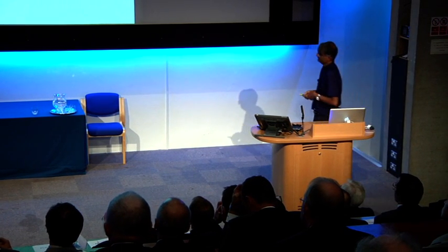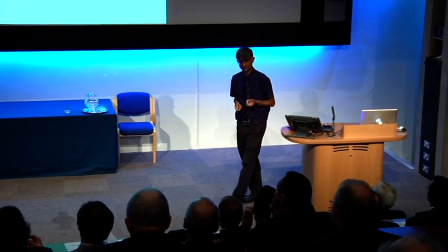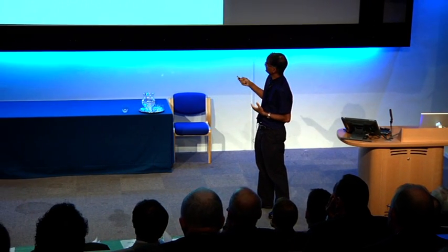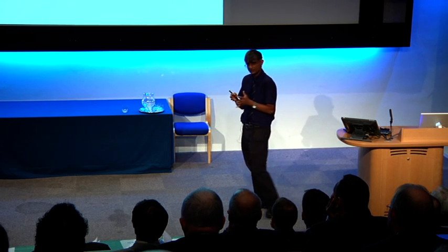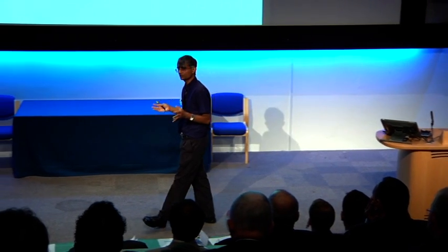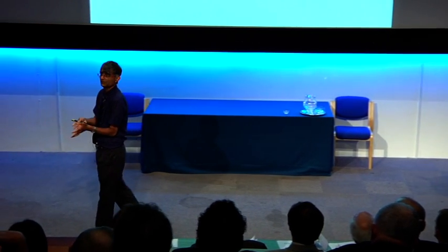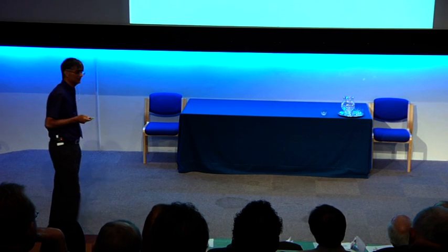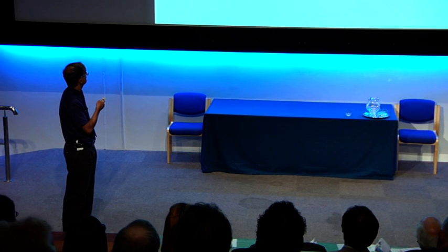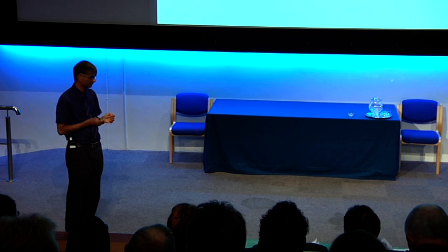And the reason why this is particularly important in strong steels is that in softer steels, you have phases like ferrite and pearlite, which grow across the austenite grain boundaries and destroy those boundaries. So there's no room left for the segregation of phosphorus to the austenite grain boundaries. But with strong steels, where we generate martensite or bainite, this involves a deformation to change the crystal structure. And that deformation is like a military transformation. The atoms move in a systematic way. That means they cannot cross grain boundaries.